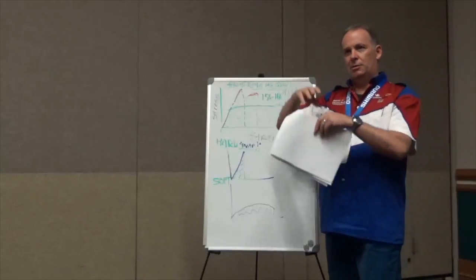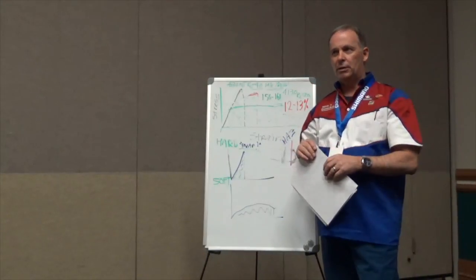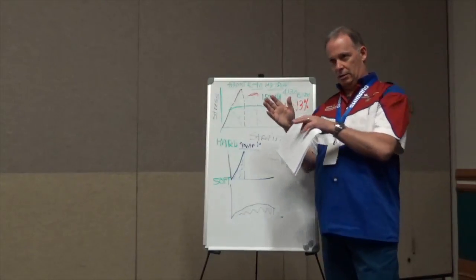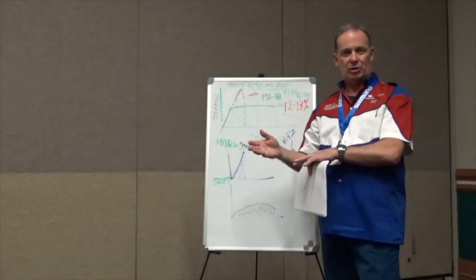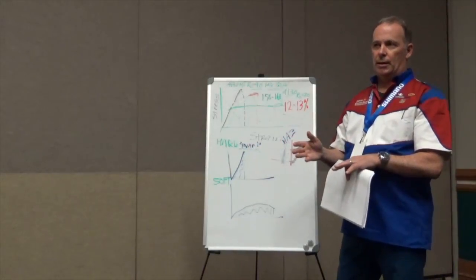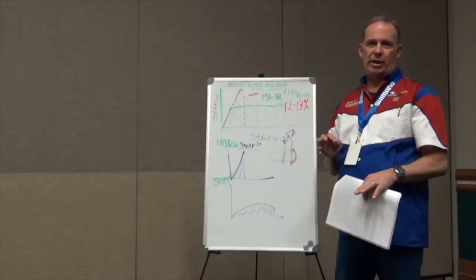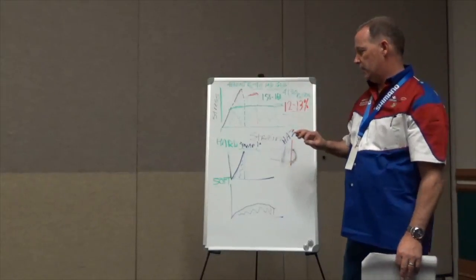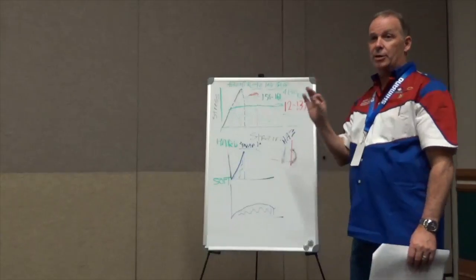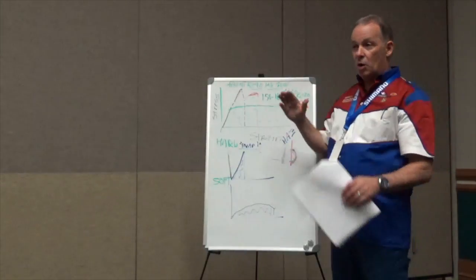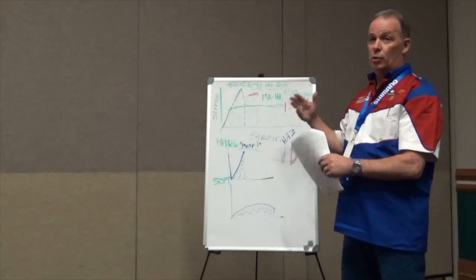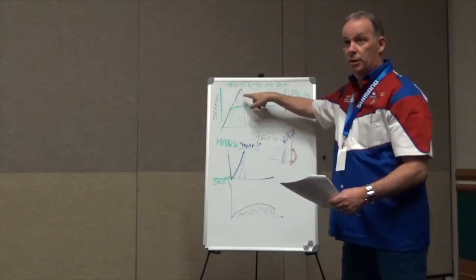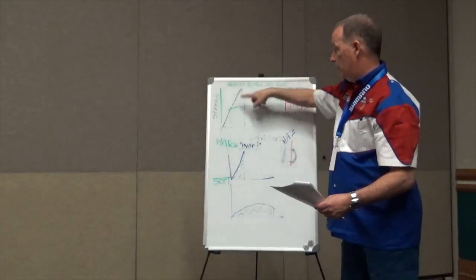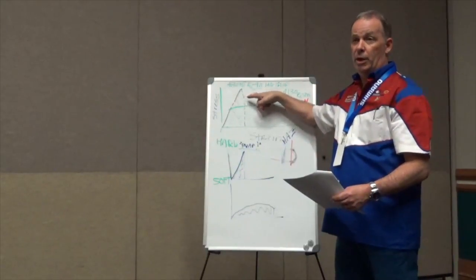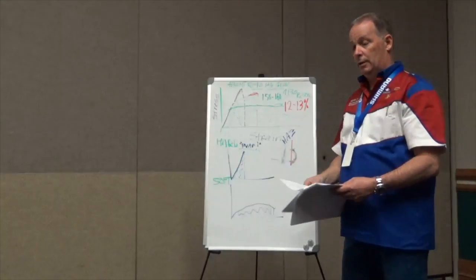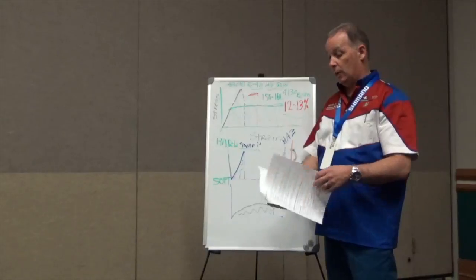If the range was wide on failure, that meant that the people making the tubing did not have good control of the process, whether it was in a heat treatment phase or in a draw step, or if they didn't use clean material. The best way of looking at the final outcome when you do a test like this is to look at standard deviation, and we were looking for really tight standard deviation. Some manufacturers, actually the ones we represent, had the tightest standard deviation. Most of the others were pretty good. There were some that had very wide standard deviation, which to us, even though their values might have been pretty good on average, meant that one tube was substantially different from another. And so we wanted to make sure that we didn't have that kind of process variation when we were buying tubing.